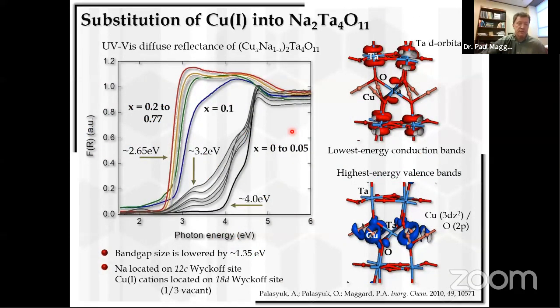So here's a UV-vis spectrum when you do that, replacing sodium 1+ with copper 1+. Copper 1+ is d10, and it has relatively high energy orbitals. You take the UV-vis diffuse reflectance as a function of the copper content, and you can see the edge, which begins at around 4 eV, which is the band gap for sodium tantalate without any copper in it. But with more and more copper in it, you can see the edge moves out some, right? And at around 10% substitution, a fully formed band is occurring. And so a new edge comes in, and it's in the visible region. And when we put the maximum amount of copper into it, we get the smallest band gap size of around 2.65 eV.